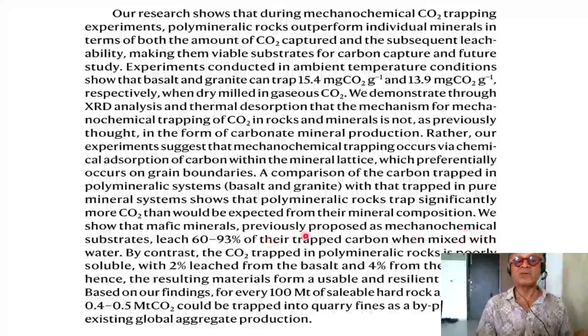We show that mafic minerals previously proposed as mechanochemical substrates leach 60 to 93% of their trapped carbon when mixed with water. So soluble CO2 gets re-released. By contrast, the CO2 trapped in polymineralic rocks is poorly soluble, with 2% leached from the basalt and 4% from the granite. Hence, the resulting materials form a usable and resilient product to put away CO2. Based on our findings, for every 100 million tons of saleable hard rock aggregate, 0.4 to 0.5 million tons of CO2 could be trapped into quarry fines as a byproduct of existing global aggregate production.